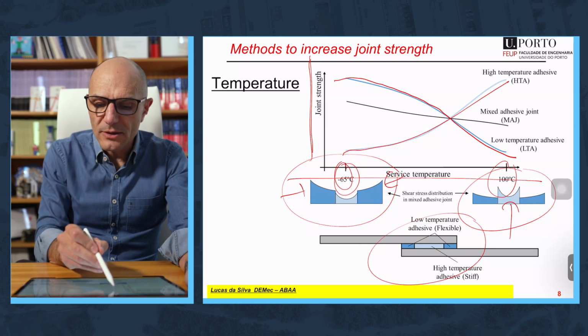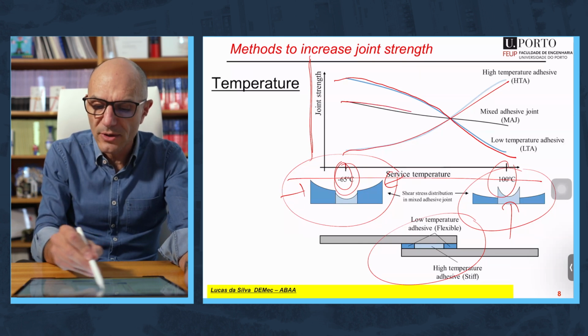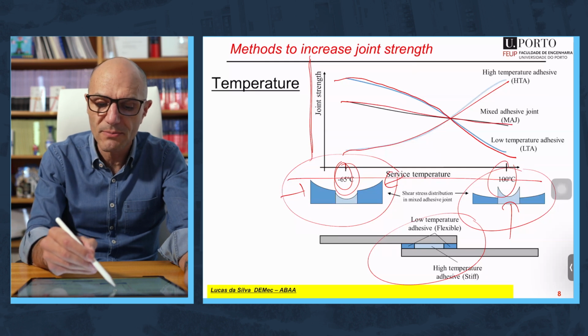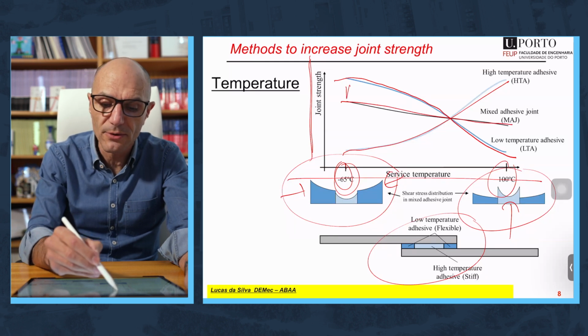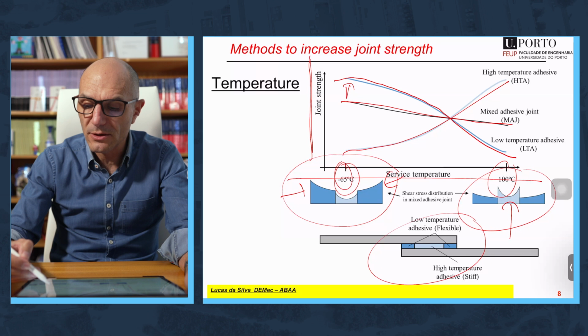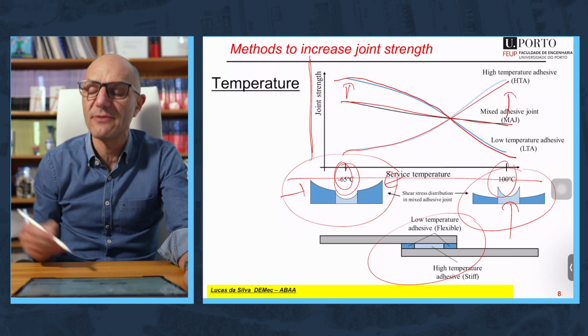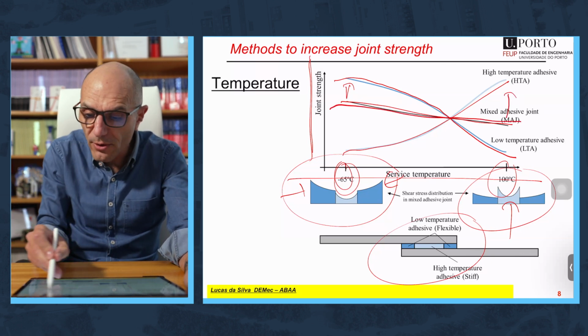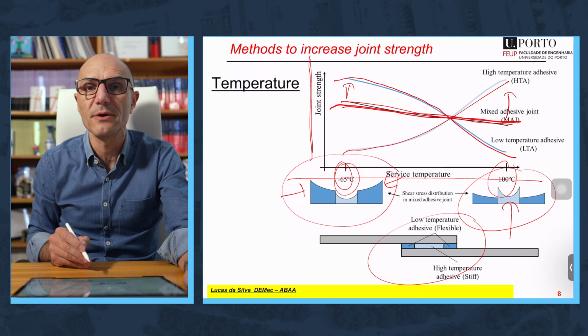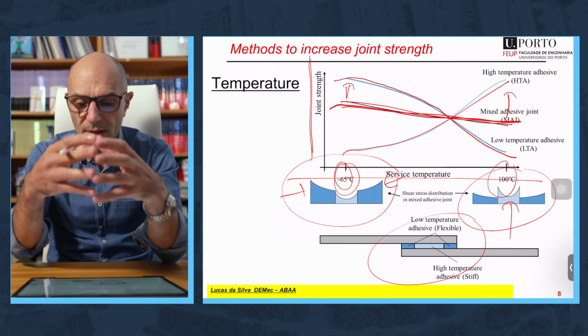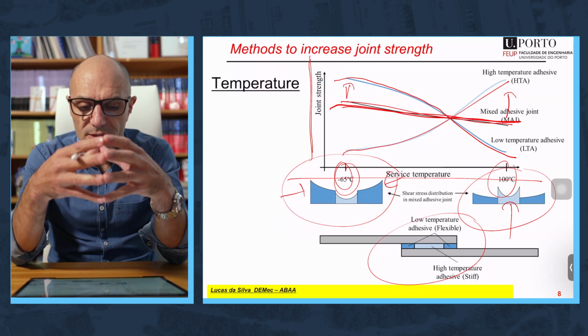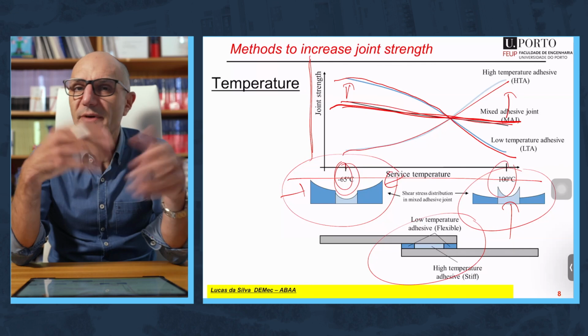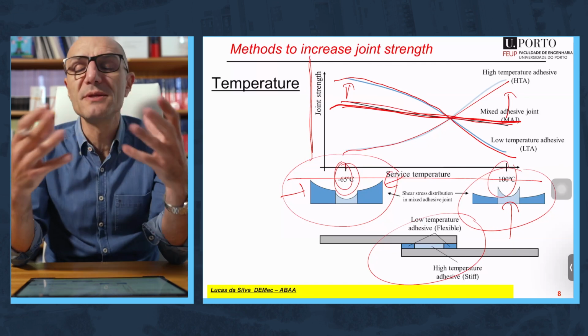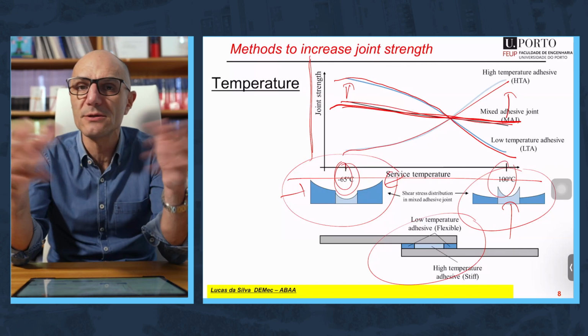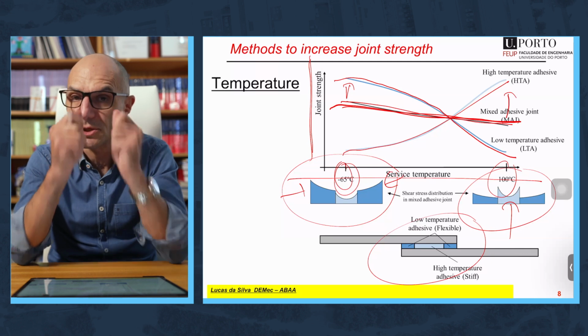Of course, when you use a mixed adhesive joint, when you use the two together, you will be here. In other words, you will not be better than the low temperature adhesive alone at low temperature. And you will not be better than the high temperature adhesive alone at high temperature. But overall, you will have a better behavior. That's the objective. So that concludes this module. Again, we have seen various methods to optimize the joint strengths, all methods that are very obvious when you understand the joint mechanics.